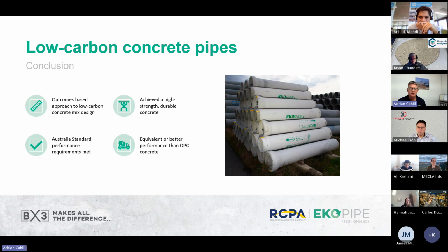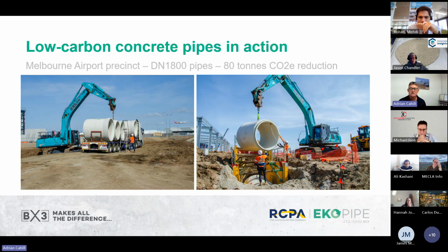So, just in conclusion, rather than seek a particular goal, we're able to take an outcomes-based approach around low carbon concrete mix designs, and that's largely a function of the ability with concrete pipes to assess the finished structure. We have achieved, and do achieve, a high strength and durable concrete, meet all of the relevant Australian standards performance requirements, and we can demonstrate that we get equivalent or better performance than we get with a standard Portland cement-based concrete.